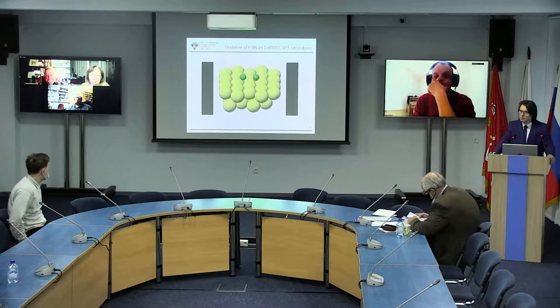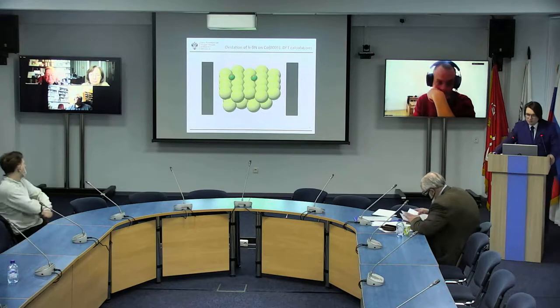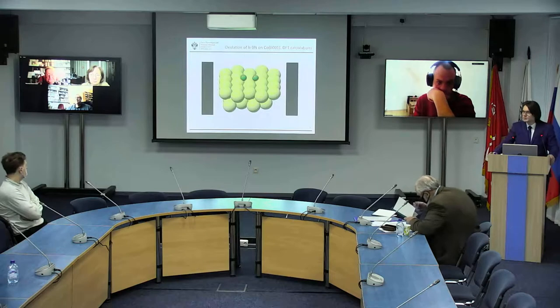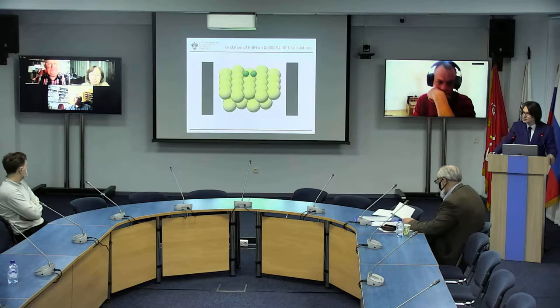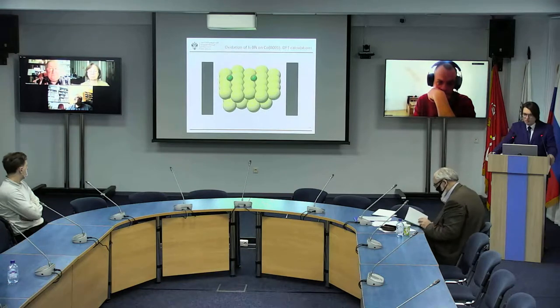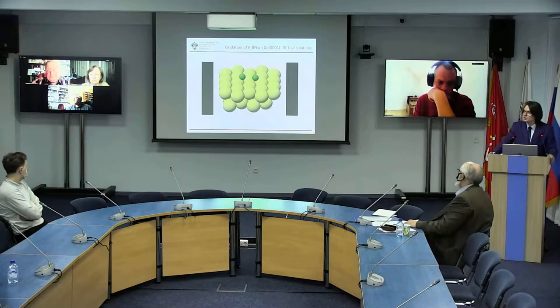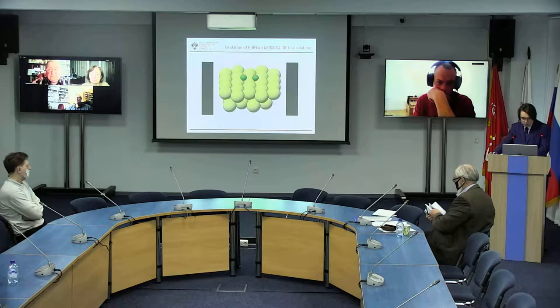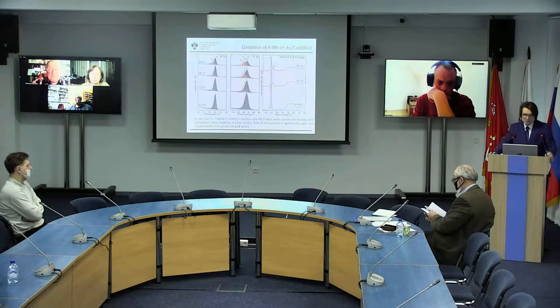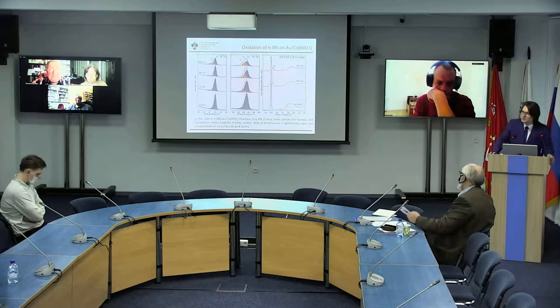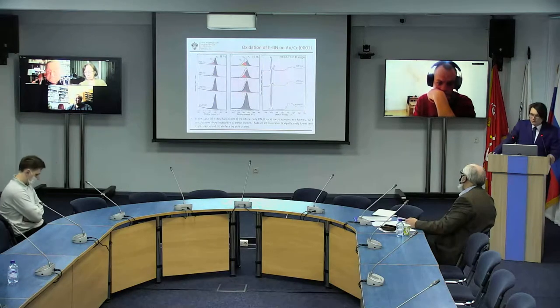In order to confirm this hypothesis, we carried out appropriate DFT calculations on the adsorption of oxygen molecules on the cobalt surface, and we see here that during the relaxation of this calculation, the oxygen molecule is indeed dissociated into atomic oxygen. And taking into account the increased heating temperature, the probability of this process is increasing.